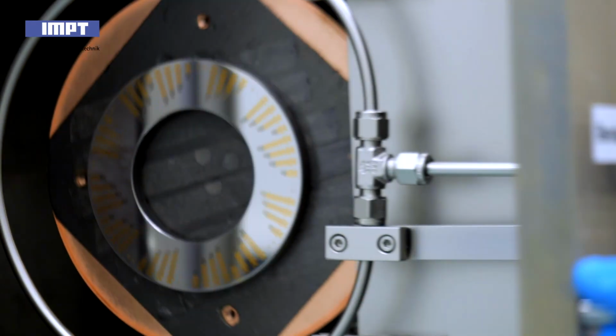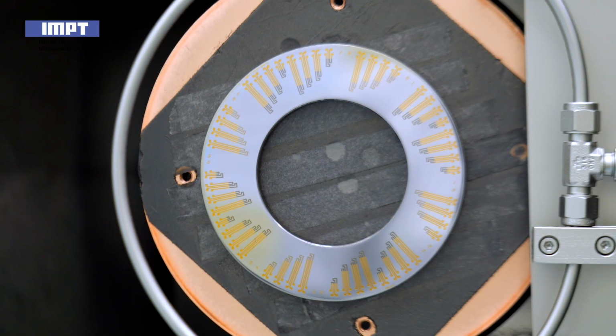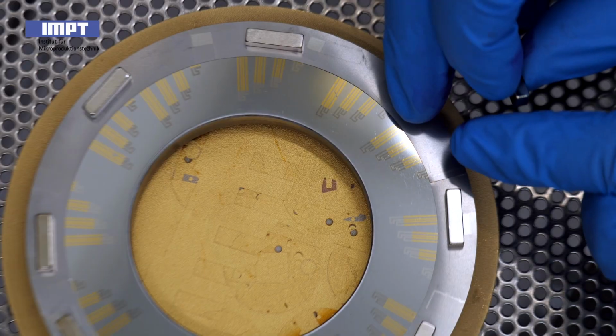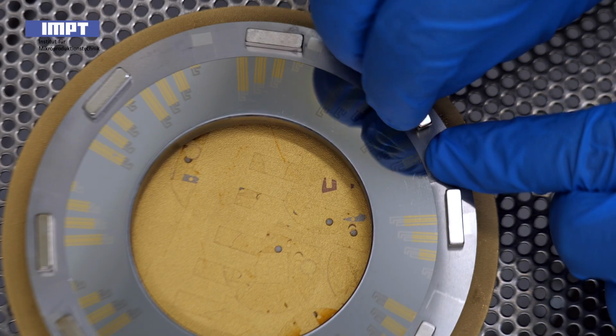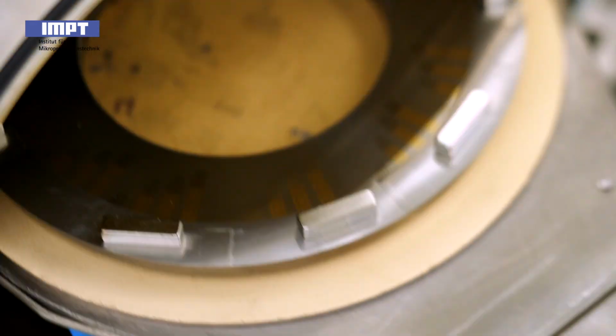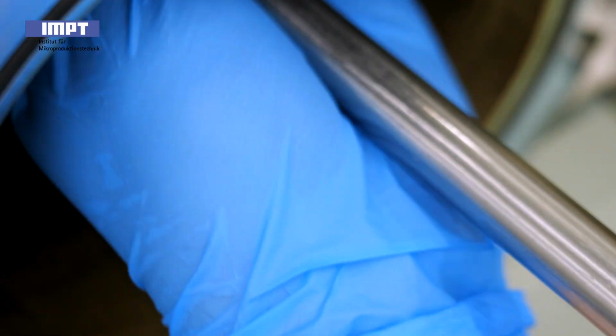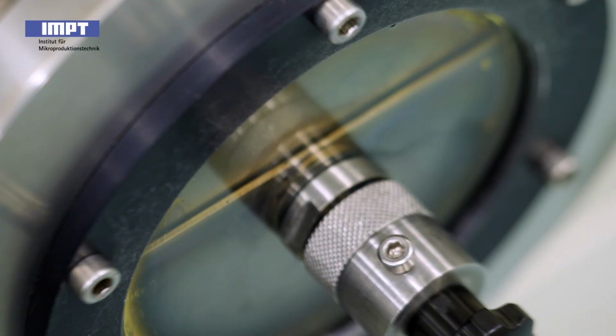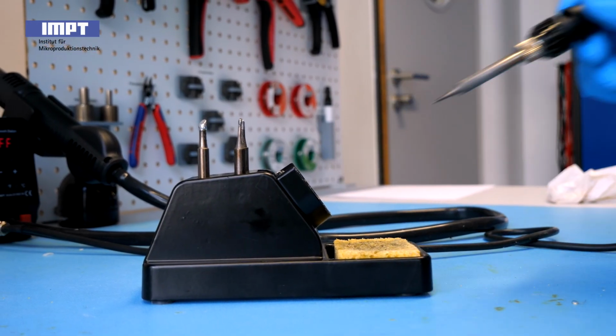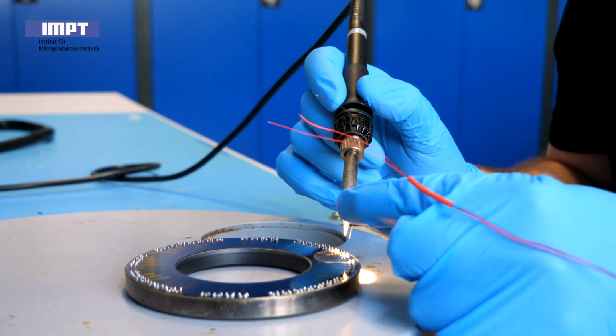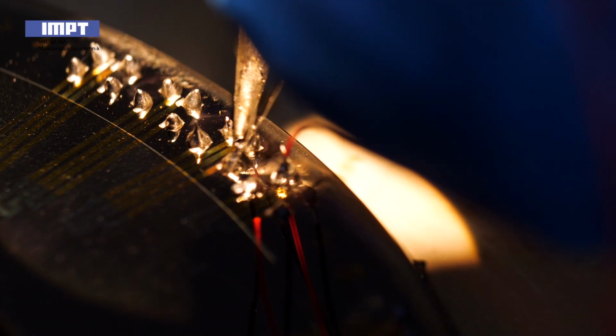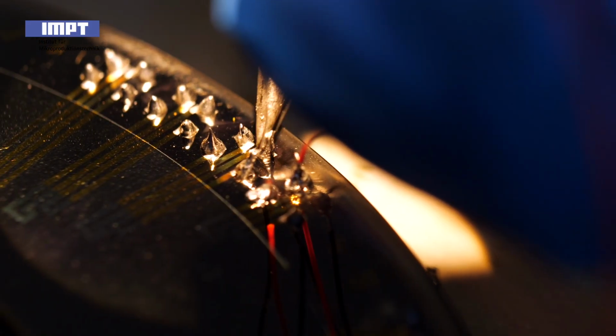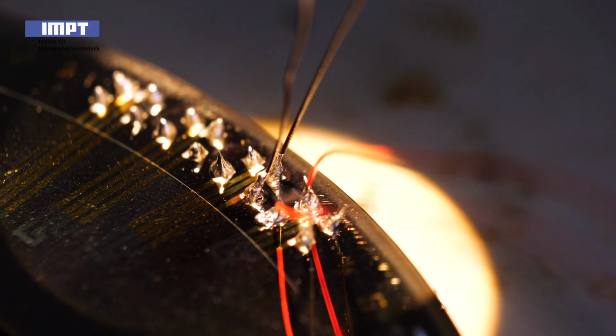After removing the photoresist from the remaining sensor structures, the contact pads are protected by another shadow mask. The sensors are finally coated with a transparent wear-resistant layer of aluminum oxide. This completes the production of the thin film sensors on the bearing washer. Now, electrical contacts are established by soldering, enabling the sensor characterization in terms of their nominal resistance and their TCR values.